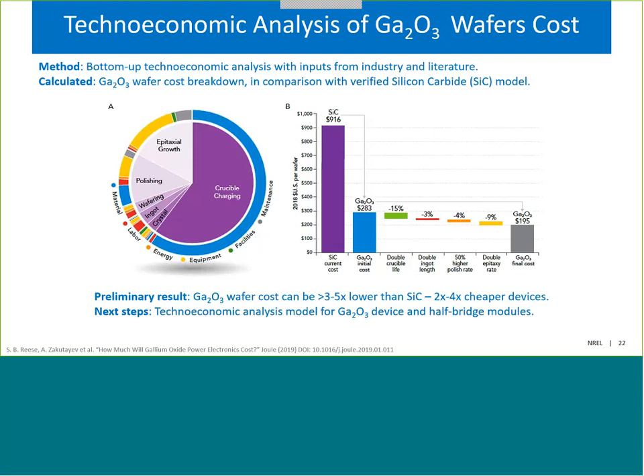The main takeaway from this is that they are predicting that gallium oxide wafer cost can be anywhere between 3 to 5 times lower than that of silicon carbide, which can result in about 2 to 4 times cheaper devices. And so there seems to be a path towards decreasing that cost. This work was published in the journal Joule, which I referenced there if you have interest in that.